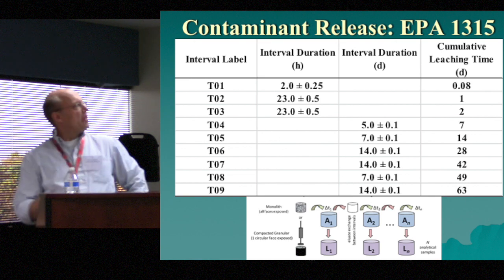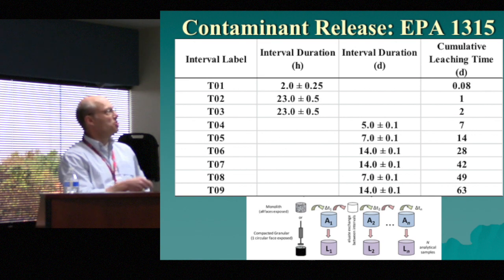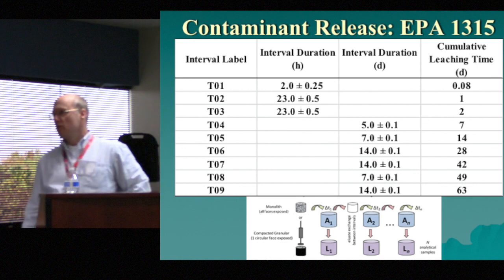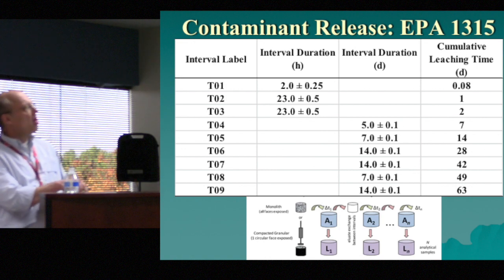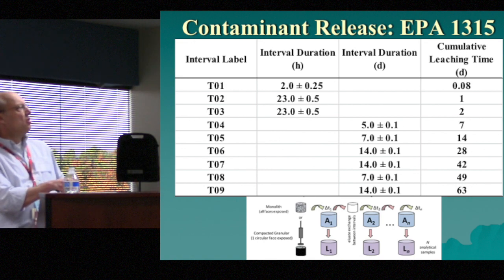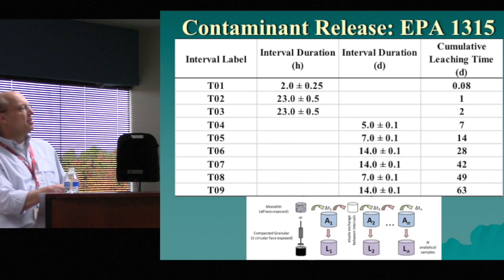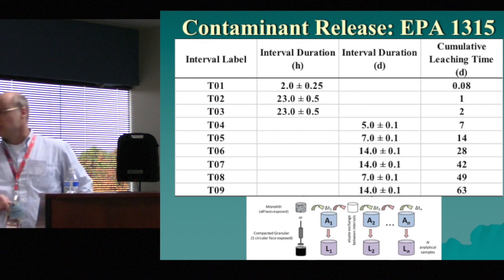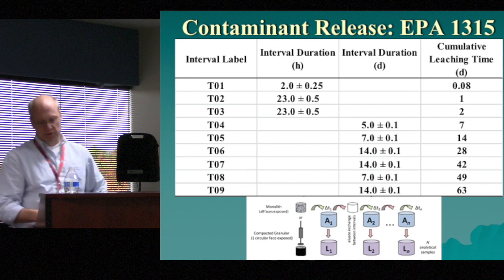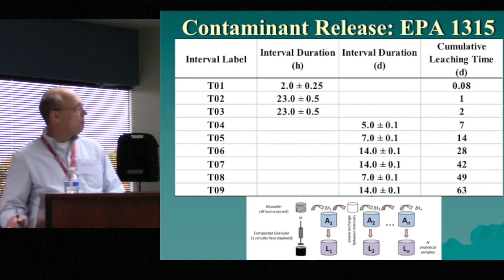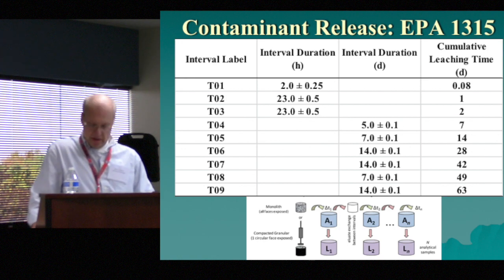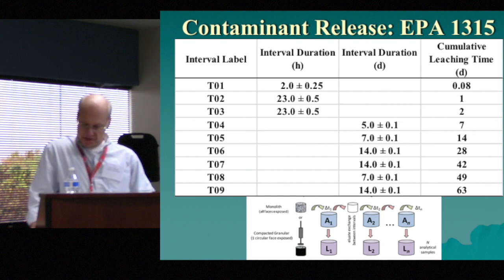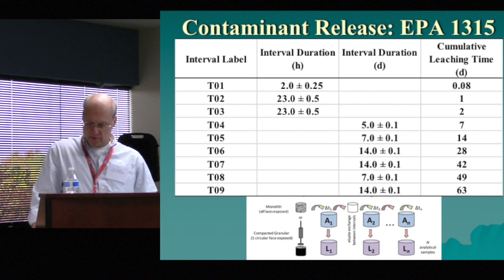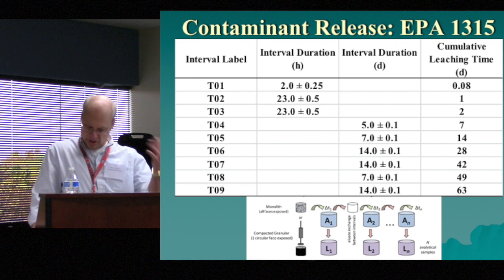So if you run the EPA 1315, what you do is you take 9 samples over time, and down here is a diagram from the actual method itself. What you do is you take the monolith, you put it in the solution for a set amount of time, then after you put it in a new solution for a set amount of time, and you do this over and over again, and you take those solutions, and that is what you analyze then at the end of the experiment. And so you take 9 samples over 63 days. Next slide.